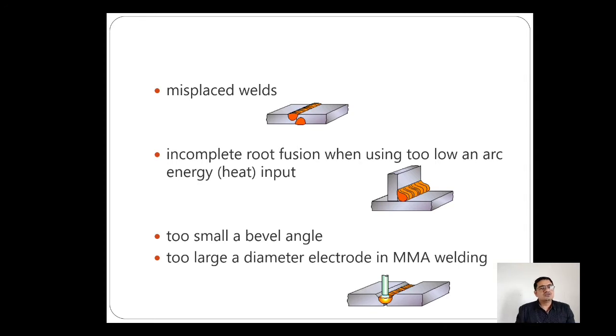Then the third one, you can see, friends, is misplaced weld, when the welder is not properly aligning the welding plates, and one welding plate bevel is on a different side, and the opposite side of the parent plate has the bevel created on another side. So it is a problem of compound bevel. The compound bevel must be straight, or you can say in proper alignment, so the penetration problem will not happen. Then next, you can see the incomplete root fusion when the arc energy or heat input is too low.